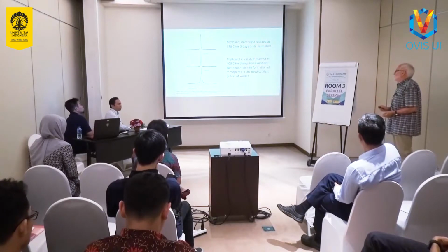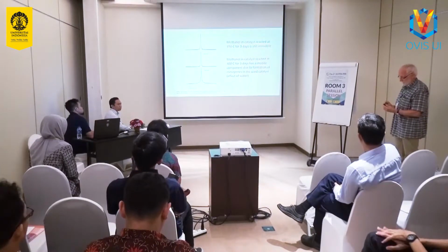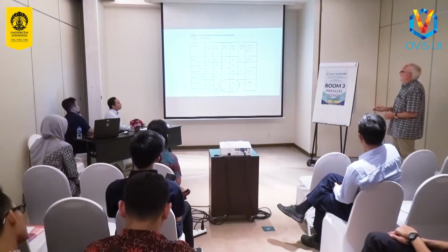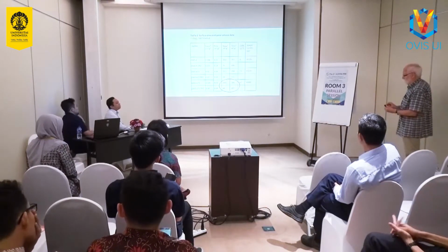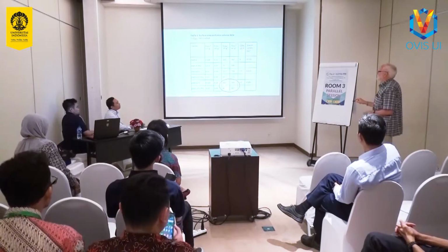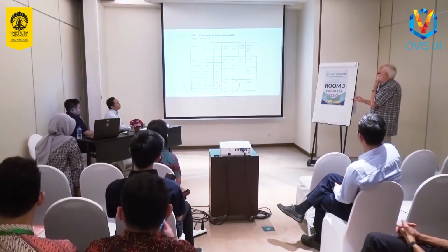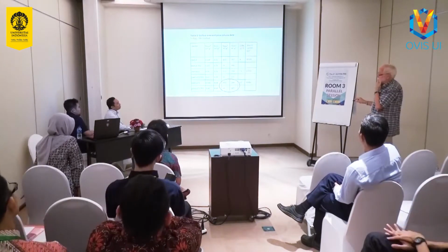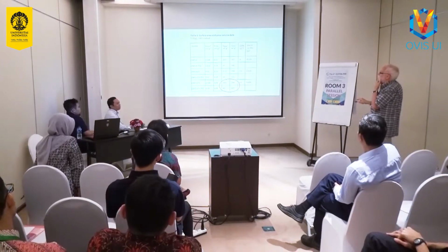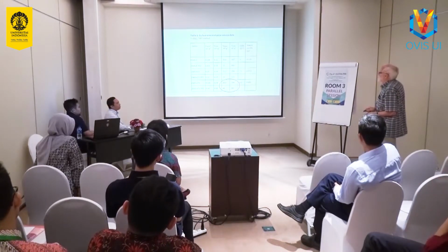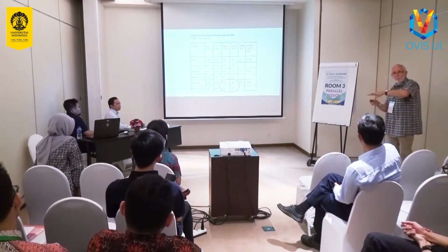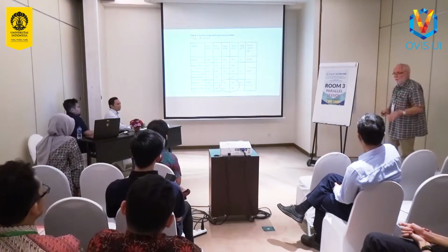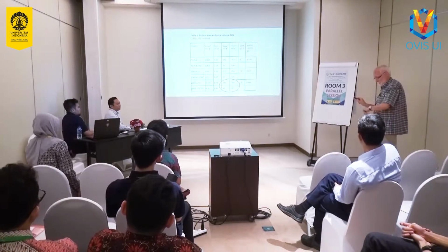Steam will generate mesopores in the zeolite. And we can show that by the conventional way of doing surface area and pore volume analysis. And you see here that when we go to 400 degrees, we've generated a significant mesoporosity in the zeolite. So the mobile methanol in the 400 degree sample is methanol moving in the mesopores. It's less strongly bound than it is in the small pores of the fresh catalyst.